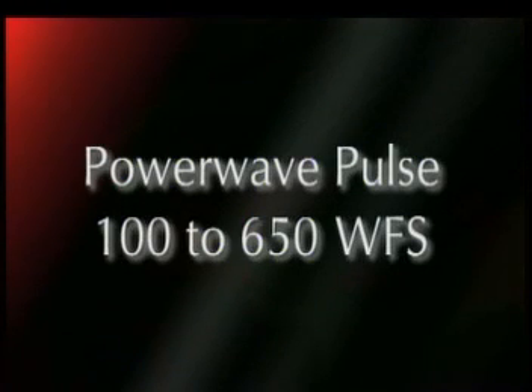The differences between the three transfer modes are significant. At the high end of the spray arc range, the arc begins to rotate and eventually becomes unstable. Now, let's run the Power Wave in the pulsed mode through the same 100 to 650 inches per minute wire feed speed range. The spray arc transfer mode is maintained across the entire range. No spatter occurs at any point along the range. At the high end, the arc remains stable and does not rotate.